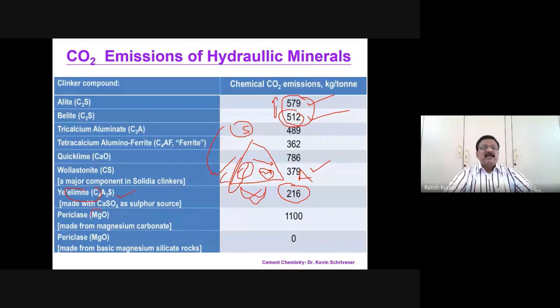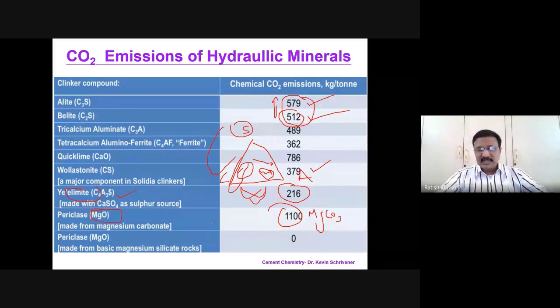The other thing is periclase, magnesium oxide. As I already told you, the magnesium carbonate which you are going to get from this is more dangerous as compared to the calcium carbonate. So magnesium silicate can probably be a good alternative. But again, the availability and the benefit we get from magnesium silicate is very, very less as compared to the danger which calcium carbonate produces. So the alternatives are not many, except to go for ye'elimite as well as belite type of cements.